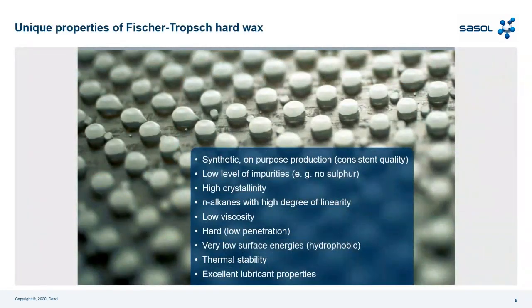So some words on Fischer-Tropsch hard waxes in general. Fischer-Tropsch hard waxes are synthetic, so they have consistent quality due to the controlled production. They have a low level of impurities, for example no sulfur, high crystallinity, and n-alkanes with a high degree of linearity. They have low viscosity, are hard, so they have a very low penetration index, and very low surface energy, which is why they give hydrophobicity and thermal stability. They also have excellent lubricant properties.